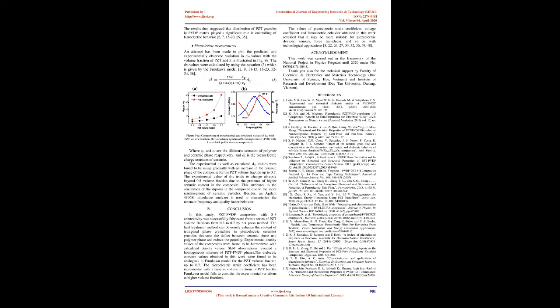Dielectric constant. Variation of dielectric constant with temperature for various volume fractions of the composite poled at 30 kV/cm is shown in Fig 6b. Steady dielectric constant values are observed in case of volume fraction from 0.3 to 0.7 till 140°C, and a steeper change is observed for volume fractions 0.6 and 0.7. Hence it is observed that the rate of variation of dielectric constant with temperature steadily increases with the volume fraction of PZT.